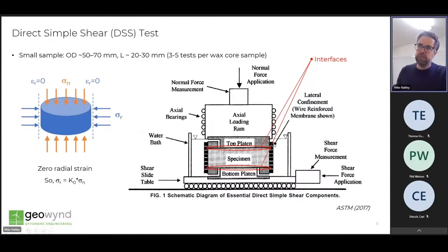The apparatus essentially imposes a horizontal displacement to the soil, which generates a simple shear distortion of the soil specimen, as indicated, and shear stresses are taken at the top or bottom boundary of the specimen, with the idealisation made that the complementary shear stresses are generated within the soil core. However, these stresses cannot be measured in the test without some very sophisticated apparatus.